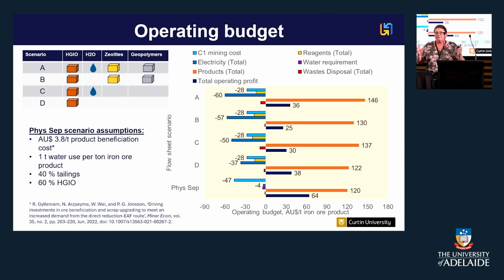And then the zeolites and geopolymers are where we aim to make as many byproducts as we can. So it's an indicator for the energy cost that goes into producing those extra byproducts. Comparing it to the same physical separation process that I compared original leaching processes to earlier, you can see that we've made great strides in having a positive operating budget for this process. This is, I think, a milestone for hydrometallurgy in iron ore beneficiation. Previously, we could see that it would be great if leaching was cost effective, but there was no way that it was. But with integrating salt splitting, we think that it may be feasible.